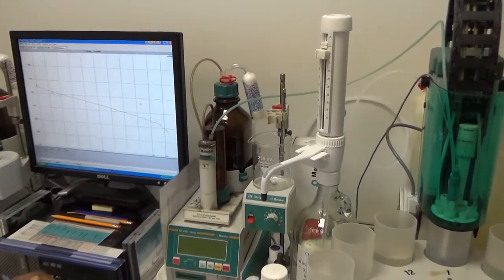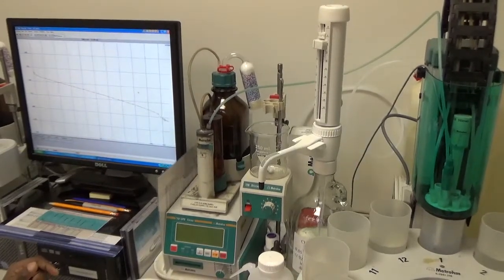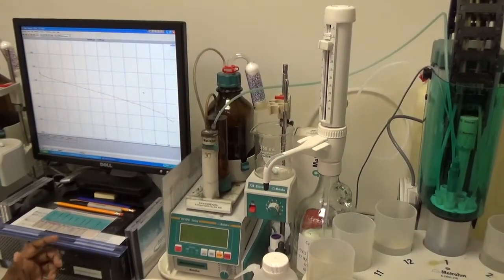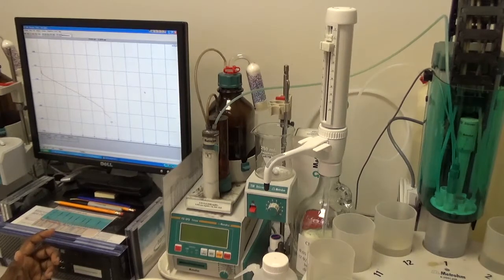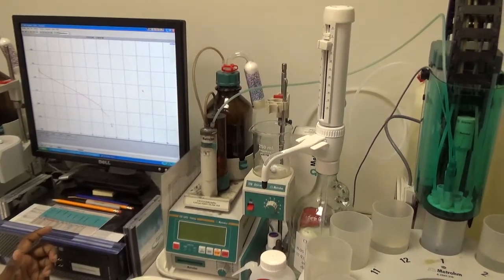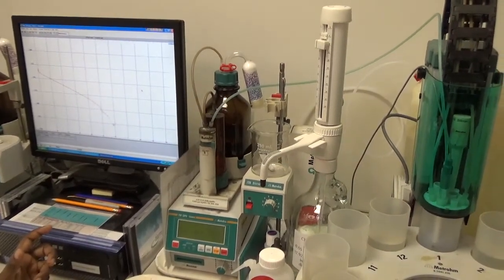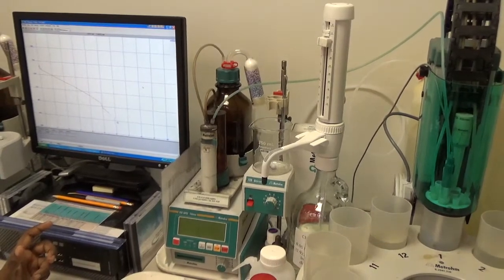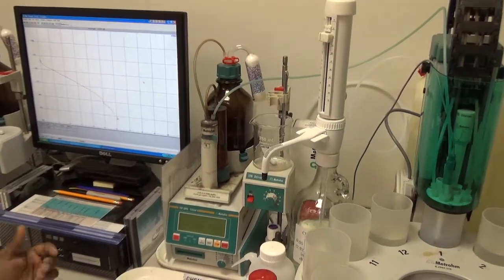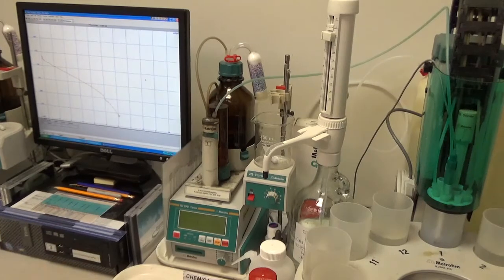Now it starts dispensing again after it fills the middle cylinder. And you can see how the titration plot is changing the slope as it adds more and more silver nitrate. The slope will get steeper and steeper, and the steepest point in this graph is the equivalence point, which we use to determine the chloride content.